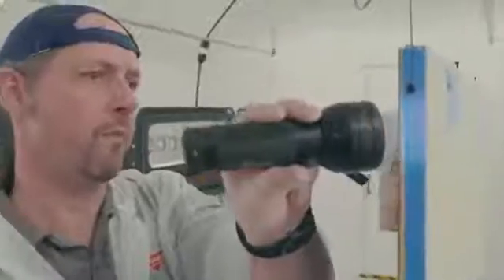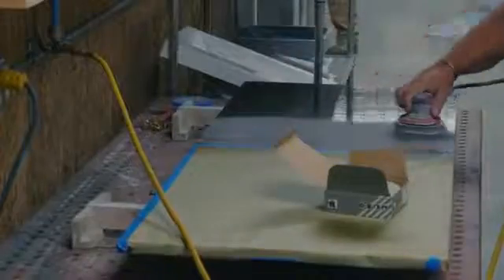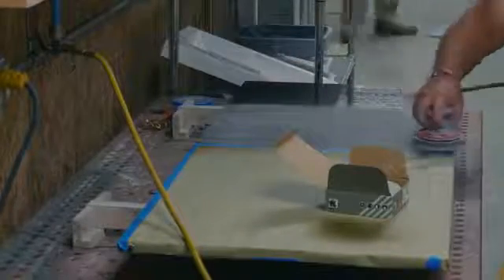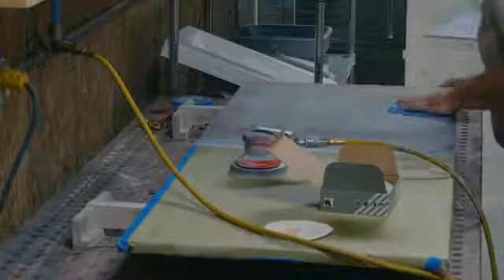After allowing the sealer to fully soak in, the surface is cured using our very affordable UV curing lamps. The seal coat is then sanded with 400 grit paper to flatten the surface, scratched with a scotch-brite pad, and wiped with 91% isopropyl alcohol to prepare for the build coats. This sealing stage takes no more than 30 to 40 minutes for a fully cured application.